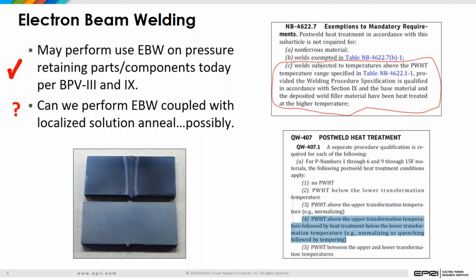Can we actually perform it with a localized solution heat treat? Today, I'm going to say possibly. We've got some development to do around that. Now, what you see on the bottom of the screen here is an electron beam weld that's shown in the upper part of the photograph, and then the lower photograph is one that actually went through a solution anneal, quench, normalization, and temper. And that basically eliminates any evidence of the overall weld itself.